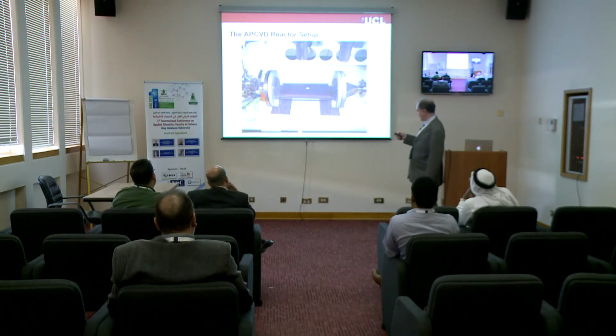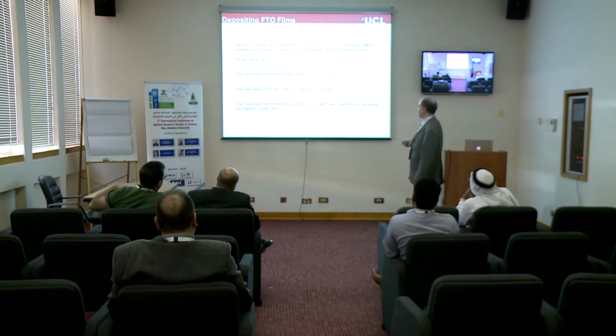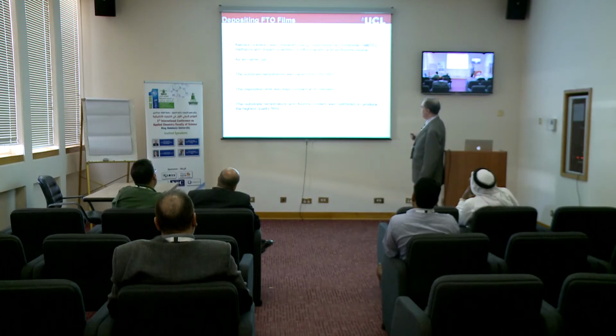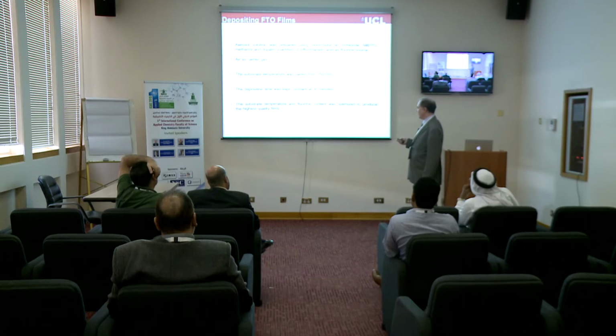So this is our reactor. Have a look at this reactor. It looks nice and clean. I'll show you later on what happens after various runs. And we've deposited our fluorine-doped tin oxide films. We use monobutyl tin trichloride as our starting material, and we use trifluoroacetic acid as a fluorine source. And our depositions were done between 350 and 550 degrees C for about 30 minutes.